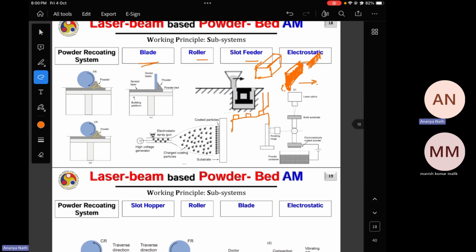Now sometimes it may happen that there is warping in the part, there is a defect, and the part is now looking like this instead of this. Instead of A, the part is looking like B. So there is an extruded portion over it. When the blade moves over it to spread the powder, the blade gets ruptured by the edges of the printed part because of the process parameter optimization, and you can easily erode your metal blades.